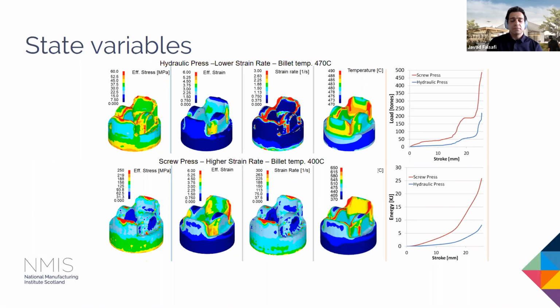So again, state variables at the end of the forging, and you can see also the load profile for the screw press and hydraulic press versus the stroke. Also the energy required for the process on the right-hand side. And one of the most important things which is different between the 2 cases is the strain rate. You can see that it's something around 200, 300 times higher in case of a screw press. And that's because it's a fast-acting process, and the material flows very, very rapidly into the die cavity.